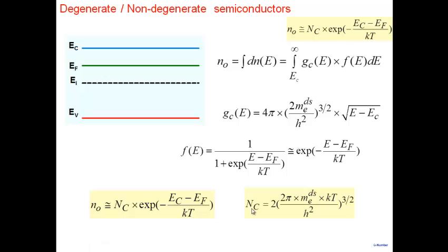And if NC becomes low, what are the implications for donor ionization? The right-hand side of that expression is becoming low, so it becomes difficult for donors to get ionized. So, you are getting that high mobility due to small effective mass, but it's coming at a price. It's coming at a price because Ni is very high. Ni becomes very high, so it's very sensitive to temperature.